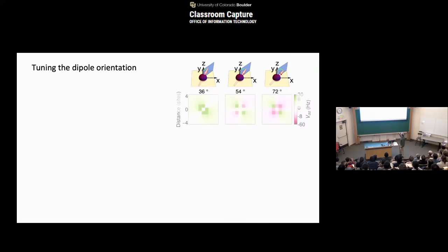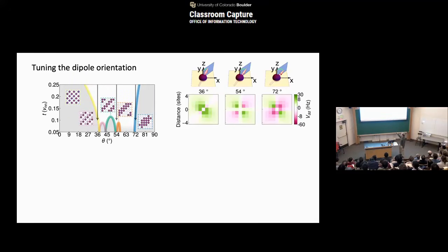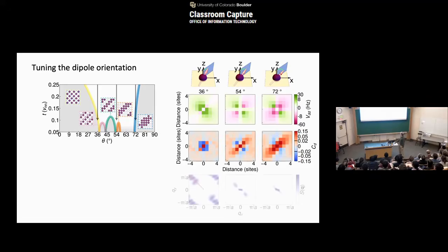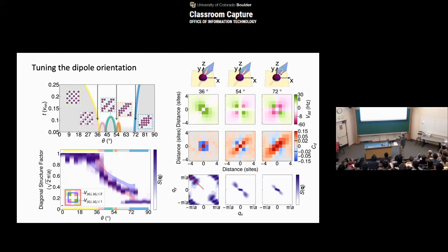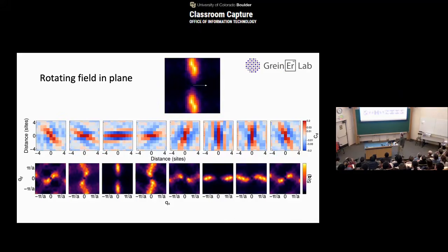It turns out if you tilt it a bit out of the plane, then the actual ground state does become a diagonal stripe state. And in fact, there's a whole zoo of different states here. And we started exploring this. Let me not go too much into detail, except for saying that what's kind of cool is seeing any diagonal stripes already shows you that we are not just sensitive to next neighbor interaction, because for diagonal you only have next nearest neighbor. But this even goes beyond, and we can only make this agree with theory if we go beyond nearest neighbor, next nearest neighbor, and if we even go beyond that, then we can make this agree with theory. So this is really dipolar interaction, anisotropic dipolar interaction that we are showing here.